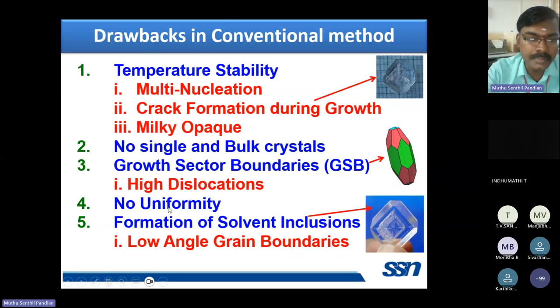And we cannot get high uniformity in the conventional method grown crystal. And the entrapment of solvent inclusions into the crystalline matrix is responsible for observing this kind of low angle grain boundaries. So not only sulfamic acid and TGS single crystal, almost all the conventional method grown crystals have these kinds of issues like multinucleation, microcracks, milky opaqueness, grain boundaries, high dislocation density, no uniformity, solvent inclusions, and so on.